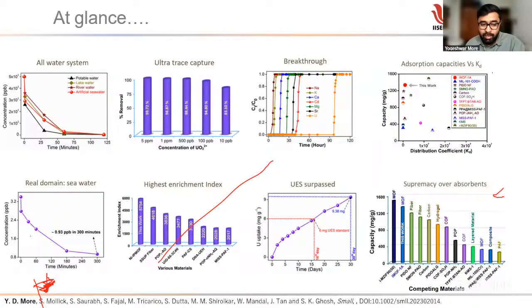So we are now able to supersede this commercially available material, and hence now we can decide our rate of adsorption, whether it is globally competitive. This is called UES, the uranium extraction standard, set by the International Atomic Energy Agency, which decides that if any adsorbent is going to be used for uranium extraction, it should extract a definite amount of uranium in a given time per gram. So what is the UES standard? The UES standard is 6 milligram.